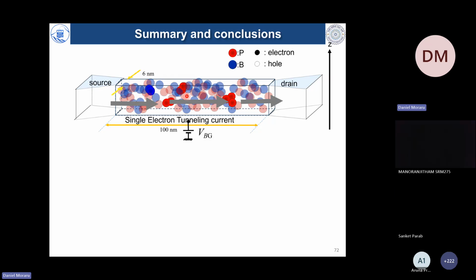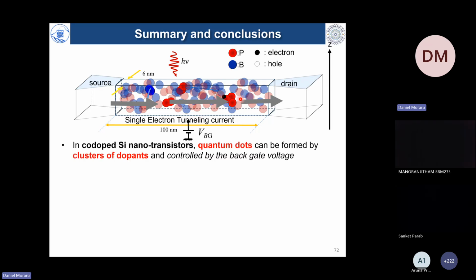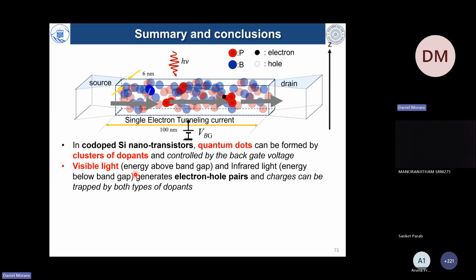The situation is very complex in these channels, but the electrons can actually travel through a few clusters, and the light can actually generate carriers nearby in some traps, affecting, modulating this transport through the quantum dots. So we should understand that co-doped nanotransistors, because of compensation, because of randomness of a distribution, can create clusters of dopants. At the same time, visible light is very useful. We can detect it very easily, but it is not very elegant in a way.